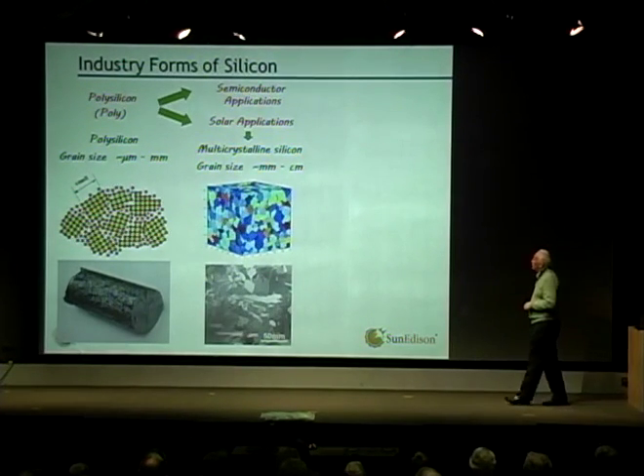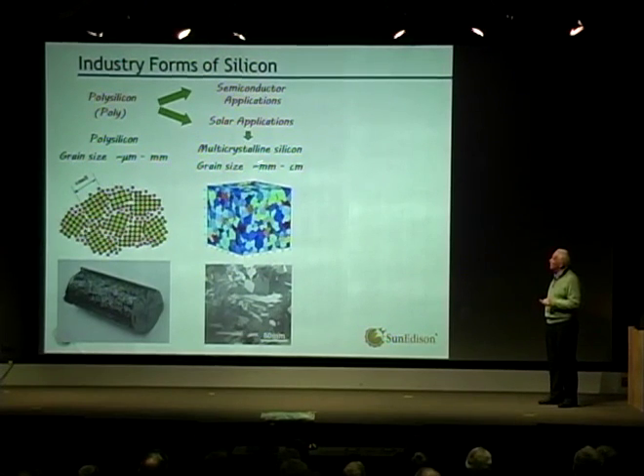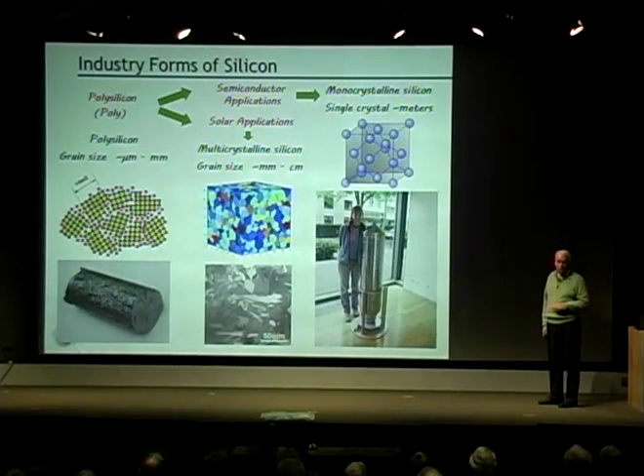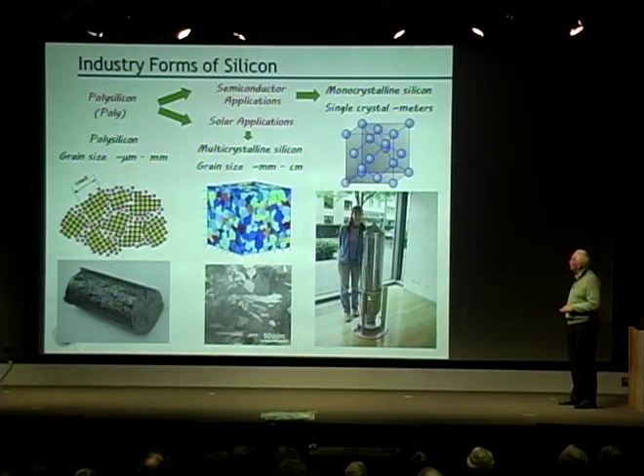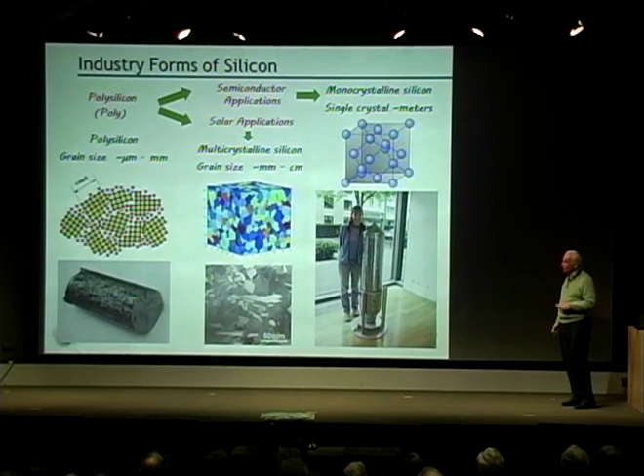There's also another type of silicon out there. We actually grow this when we're making solar cells. We grow what's called multicrystalline, and it's really similar, except that the crystalline grain sizes are now from millimeters to centimeters. In fact, when we make solar cells, we try to make those grains pretty big, so several centimeters across. If you look at a solar cell wafer, they'll be blue, but you can still see the grain sizes. We call this multicrystalline as opposed to polycrystalline. Poly is from the Greek, many, many silicon crystals. Multi means several, I guess. And then you've got monosilicon, in which case it's a single crystal. I don't know this lady, I've never met her, but I can tell you she's probably about 5'6" tall, because I do know this guy, or things similar to it. It's a bit of a guess. The size of these crystals depends on the size of the crystal puller that it came from and the diameter, how big the original charge was in the crystal grower.